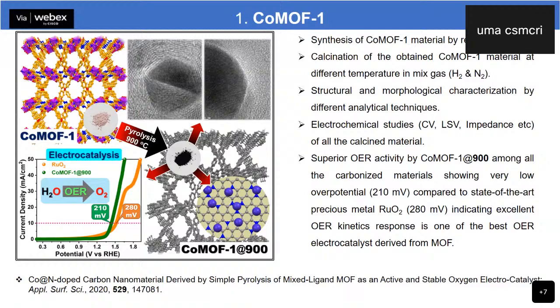Then in the case of cobalt, CoMOF-1 material was prepared by the modified route. Then after complete synthesis, the material was calcined at different calcination temperatures, from 600 to 900, that is 600, 700, 800, and 900 degrees Celsius. After complete pyrolysis, the material was well characterized by different analytical techniques to confirm the structure and morphology of the material. Then this material was used as the electrode material for HER and OER applications, and the electrochemical properties were evaluated through CV, LSV, and impedance.